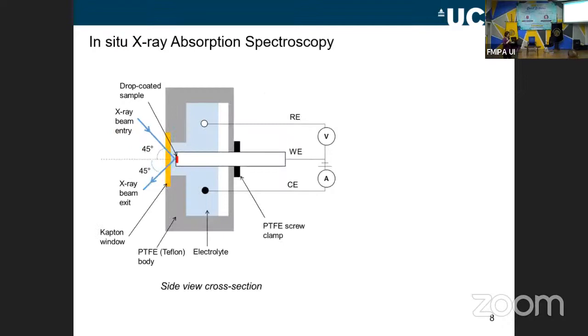The first technique that we looked at was using something called in situ X-ray absorption spectroscopy. To do this, you have to visit a synchrotron facility. You can't do this just generally in a lab. It's an absorption method. So basically you shine X-rays onto your sample and you see what energies have been absorbed. And that will tell you about what species are present in your material.